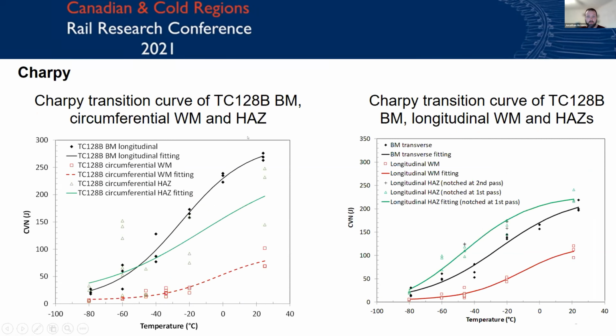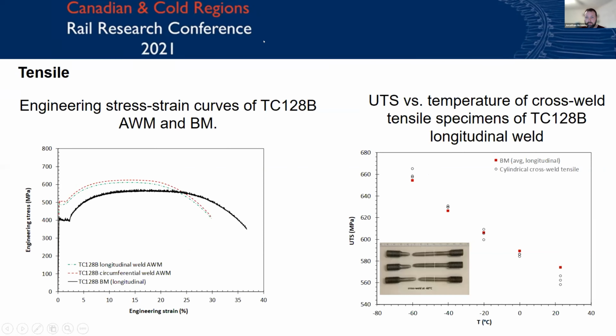On the right-hand side of your screen, you can see the UTS compared to temperature of the cross-weld tensile specimens that we studied, ranging from -60 degrees up to 20 degrees Celsius. There's a few things to note. The first is that we don't take these as a measure of the weld strength because it's a sample that contains base metal and both weld, but it does show us whether or not the strength of the weld is at least as high as the base metal.